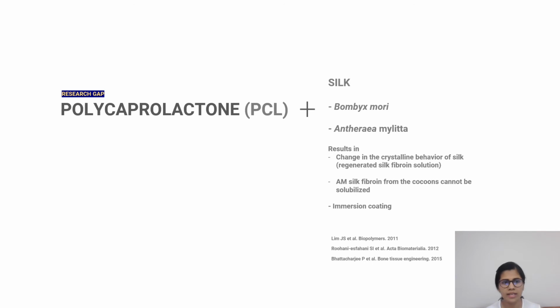So another set of literature showcases the combination of silk with PCL, and two silk variants are being used, Bombyx mori and Antheraea mylitta. In both cases, silk is used in the form of regenerated silk fibroin solution, and this solution is coated over the 3D printed scaffolds. So there are so many variables here: the coating time, dipping time, the concentration of the solution, and the penetration of the solution into the PCL scaffolds.